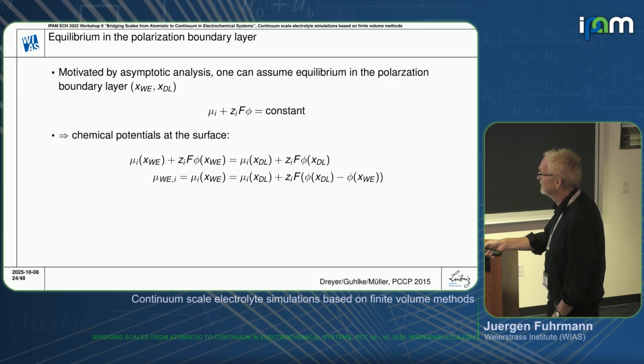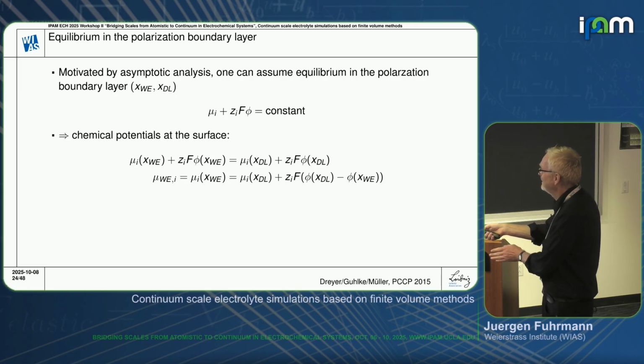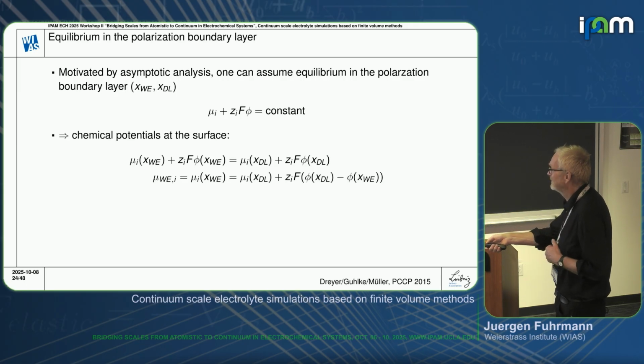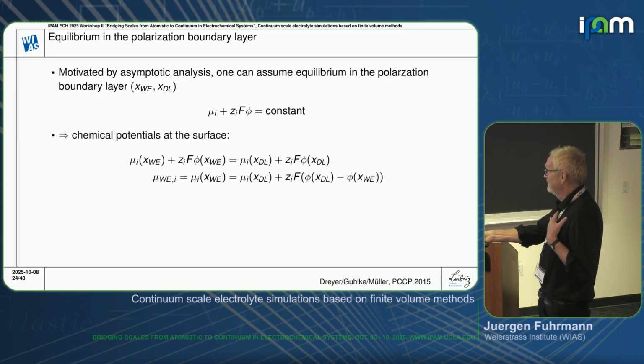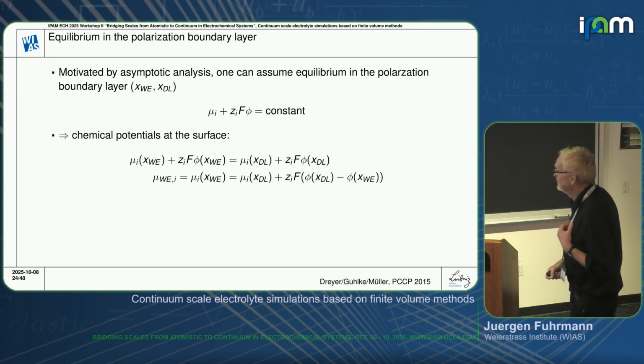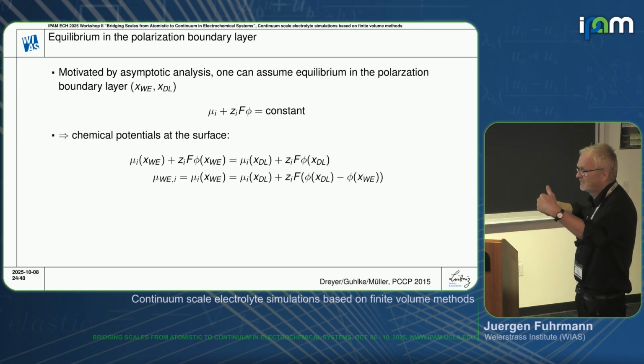So that means that the electrochemical potential at the surface is the same as the electrochemical potential at the interface between the double layer and the bulk electroneutral domain, where everything is already electroneutral. And then we can calculate the surface chemical potential from the chemical potential at the bulk side of the double layer plus the difference of the electrostatic potential over the polarization boundary layer.